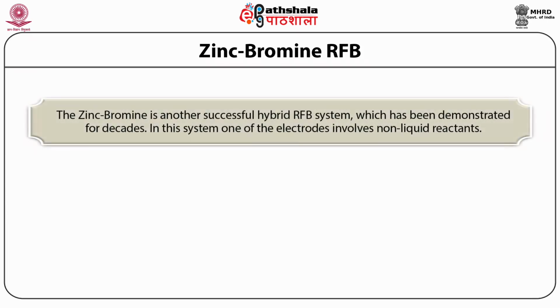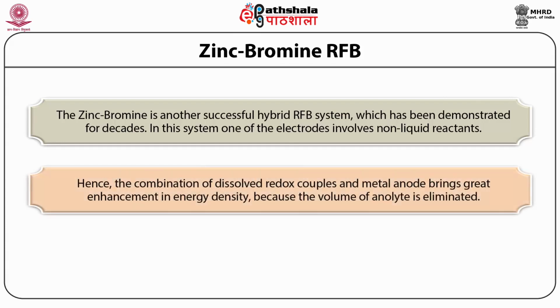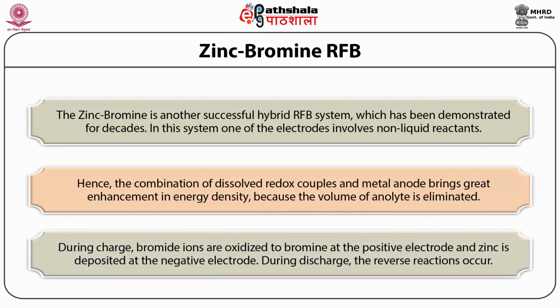The zinc-bromine is another successful hybrid RFB system which has been demonstrated for decades. In this system, one of the electrodes involves non-liquid reactants. Hence, the combination of dissolved redox couples and metal anode brings great enhancement in energy density because the volume of anolyte is eliminated. During charge, bromide ions are oxidized to bromine at the positive electrode and zinc is deposited at the negative electrode. During discharge, the reverse reactions occur.